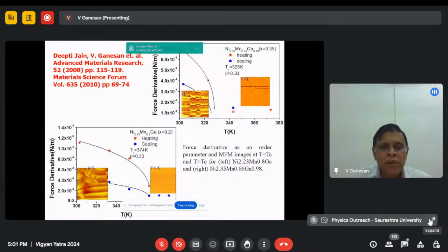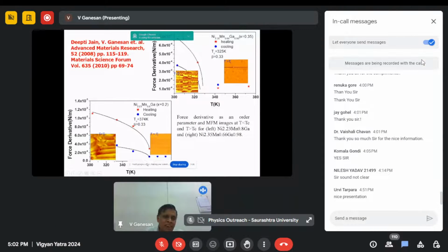That's why what we do is try to get these domains. Just go and sit on one of the domains, try to change the temperature, and measure the resonant frequency of the cantilever, how it changes. That becomes the force derivative, and these derivatives will obey a very beautiful curve like (1 minus T by Tc) squared. That works for the case of a critical exponent of a phase transition.